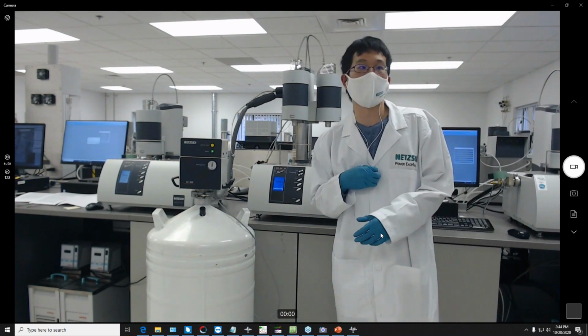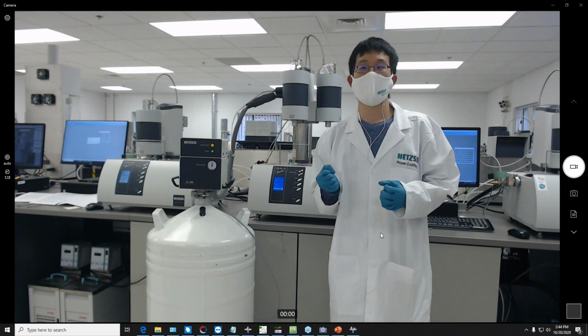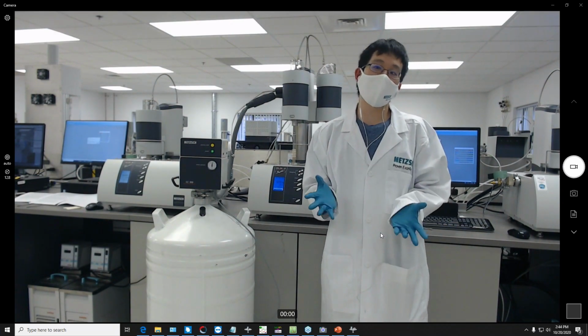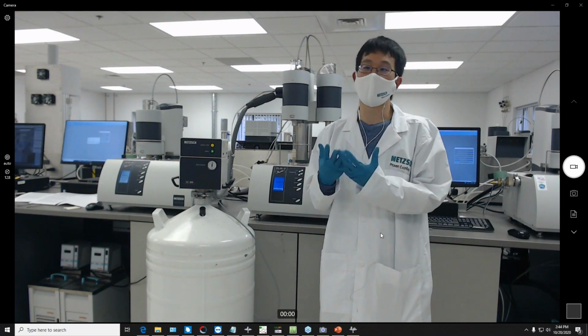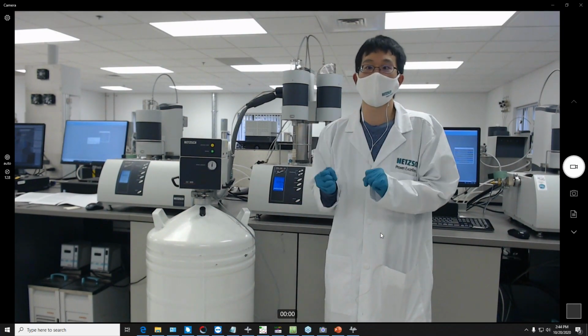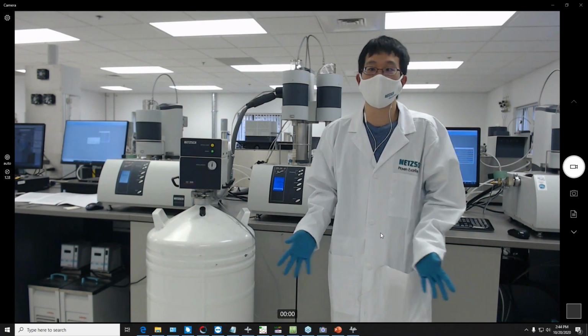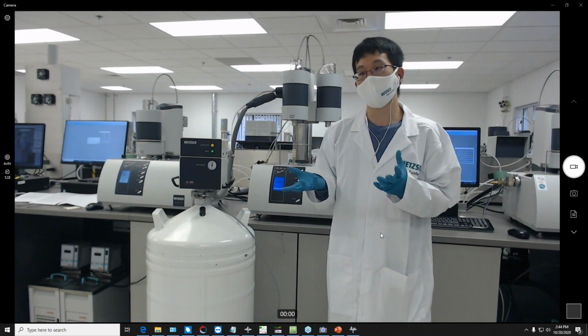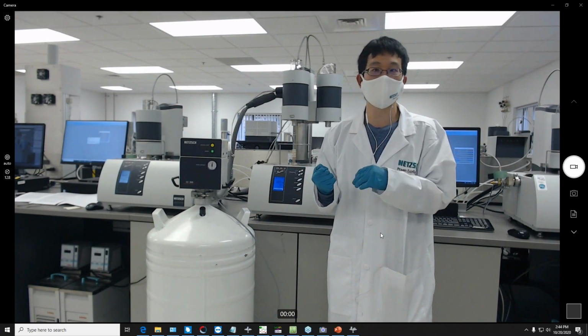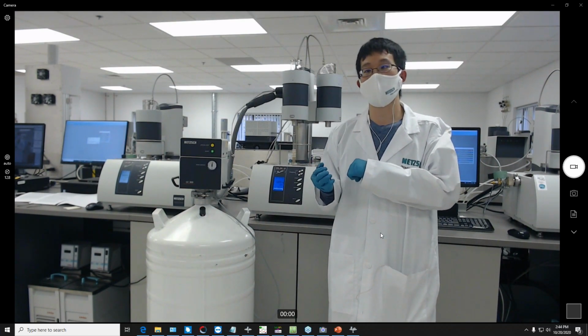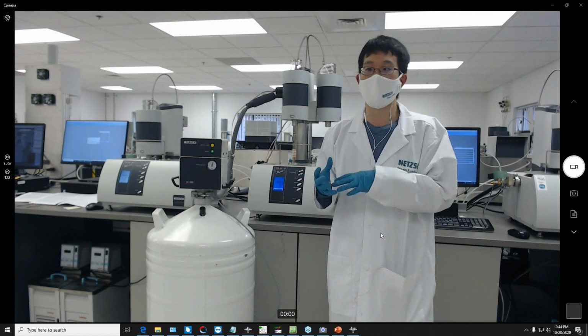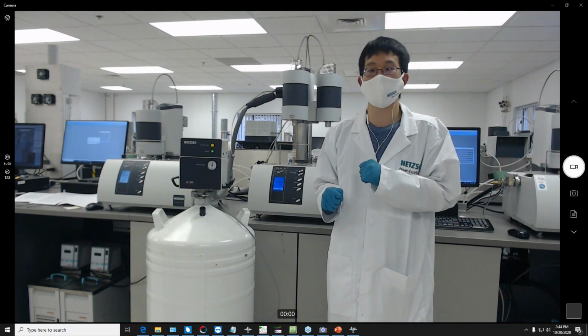Do you use auto vacuum when you switch gases for STA QMS systems? So usually you have the ability to use auto vacuum. In terms of starting a measurement for a QMS system, I'm usually operating in argon gas. Argon gas is usually much denser than the atmospheric gases, so allowing a long enough purge will push all the gases out. But you could effectively do the same with evacuation and backfill. I tend to choose not to evacuate if I'm doing powder samples because I could end up sucking some of the powder out of the crucible.